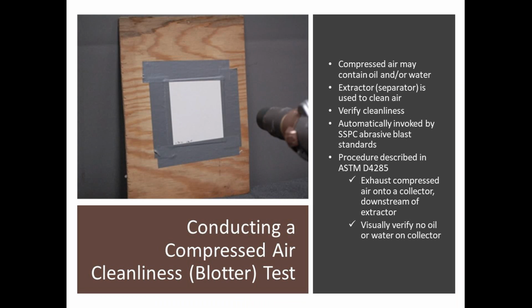This again doesn't really involve any instrumentation, but it's another important checkpoint. If we're going to use compressed air to abrasive blast clean, or if we're going to use that compressed air to blow the surface down to remove the dust from the surface, we have to make sure that compressed air is clean and dry. How do we do that? It's called a blotter test or a compressed air cleanliness test. There's an ASTM standard for it that's listed up there.